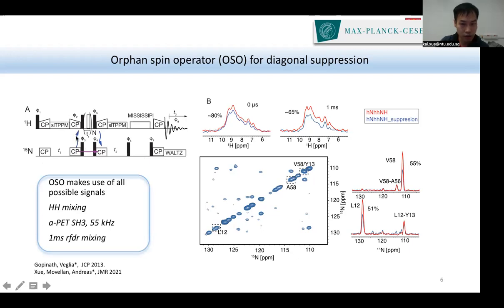After the CP transfer here, we have most of the polarization transferred from nitrogen to proton, but these CP transfers are normally not complete. We still have some polarization left over on the nitrogens. And since the signal is on X, the T2 is very short compared to T1, and this signal simply disappears, and we don't make use of these signals. And then when the signal is transferred by CP from H to N here, this signal simply decreases with T2. But somehow we can preserve this signal. These leftover signals are often called spin operators.